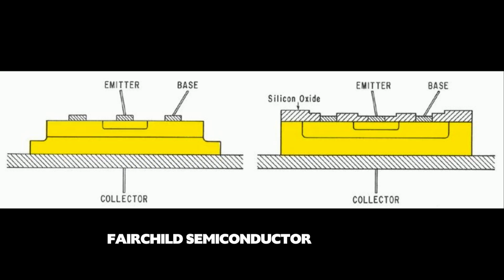Fairchild Semiconductor submitted test samples in July 1960. The transistors used Hoerni's planar process with silicon oxide passivation, fabricated on silicon wafers with carefully controlled crystal orientation and doping profiles. Each transistor was hermetically sealed in a metal can, filled with dry nitrogen to prevent any moisture contamination. Autonetics received 500 devices and began qualification testing that would run for 6 months.